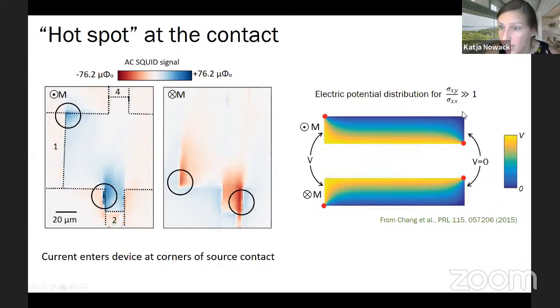And if you look at how the current is expected to flow in a device that has this, you expect that the equipotential lines, which you can simulate and are shown in this color graph here, flow from one hotspot in the contact to the hotspot at the other side of your sample. This is a graph of the equipotential lines, but the current, because of the strong ratio, essentially follows the equipotential lines. So you would expect your current to do something very similar. And we have some evidence of that happening in the devices.